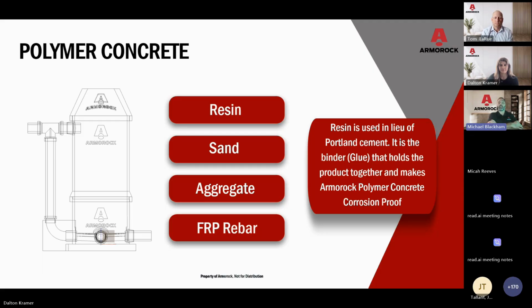And then the other major difference is instead of Portland cement and water, which is typically referred to as paste in conventional concrete, we use a special resin binder. And this resin acts as the adhesive or glue that bonds those aggregates together to form the concrete, much like cement paste would do in traditional concrete. The most notable advantage of polymer concrete compared to traditional concrete is its exceptional resistance to corrosion. That's where its strength is, especially in our sewer environments. So this strength really is the major focus of today's discussion that we're going to go into in good detail.